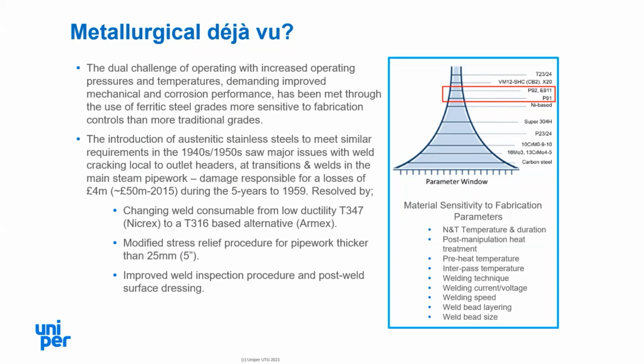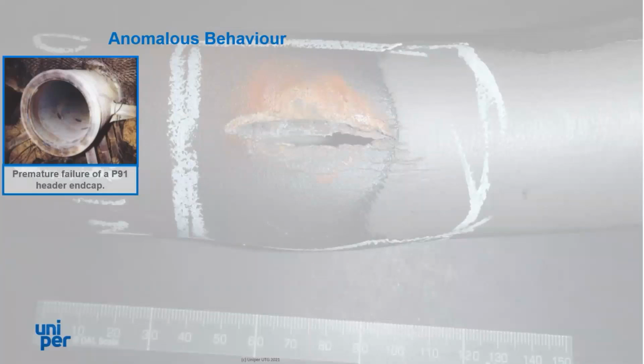We've largely seen these kind of approaches taken for the more exotic grades, but whereas grade 23 and 24 are sort of the new kids on the block, if you like, grade 91 has got rather more of an established history, but it's come with its own issues. Perhaps the first of these was during the mid-1990s. Grade 91 was seen as being the answer to a maiden's prayer as the UK industry saw a transition from baseload operation to cyclic operation with the introduction of gas-fired power plant.